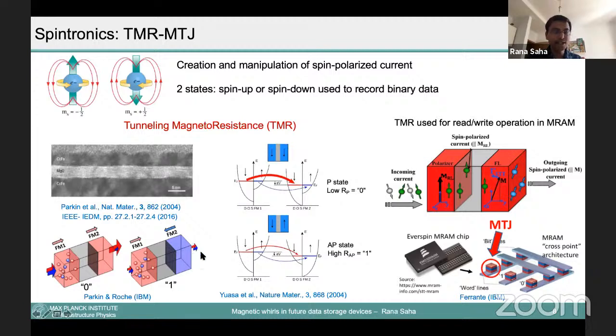But if the magnetization of this layer is down, the probability of tunneling of the electron through this thin dielectric barrier reduces. Depending on the orientation of the magnetization, this tunneling happens. So you can have two states, called 0 and 1. So this can act by itself as a memory cell unit. So what is actually done? You can use such a small structure in a cross array, in the form of MRAM, a magnetoresistive random access memory.